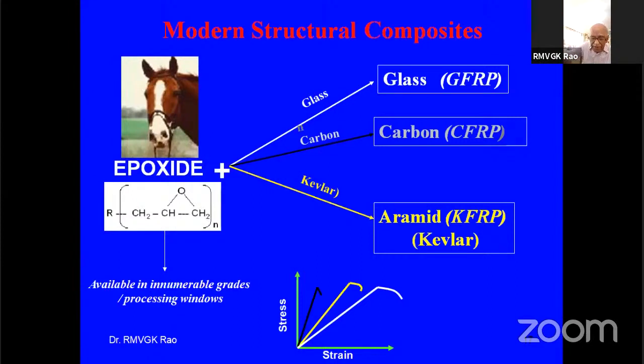And glass fiber is about 80 GPa. 80 GPa versus Kevlar 120 versus carbon about 200 to 500. So when you want extremely stiff and dimensionally very rigid structures, you go to carbon. When you want only higher strength, you go to glass. In between is Kevlar, but Kevlar has certain limitations we'll see later.